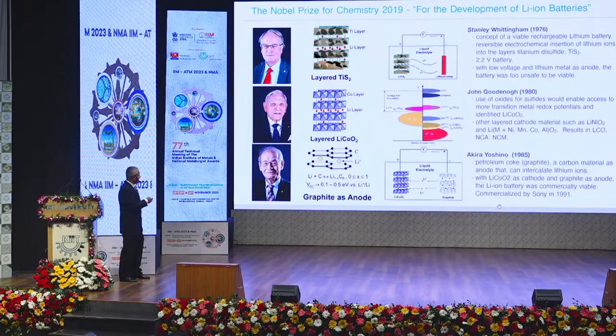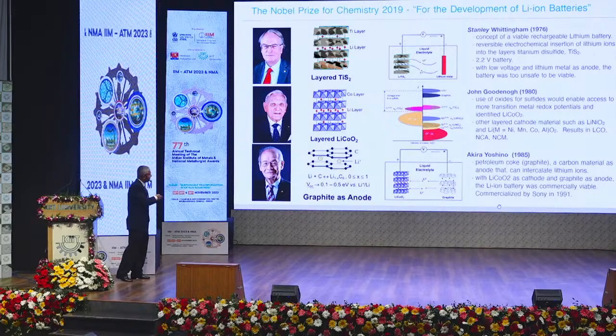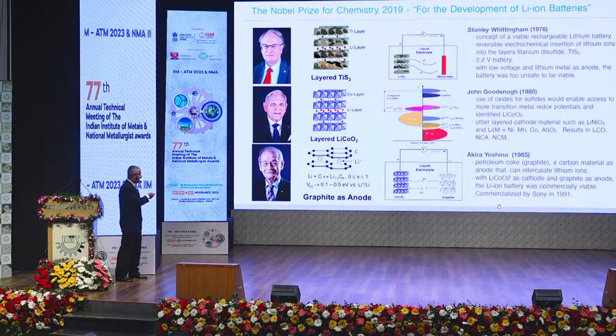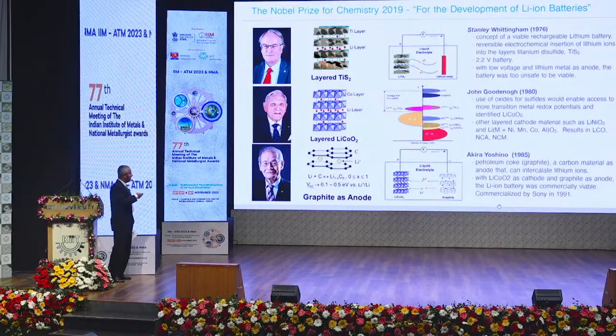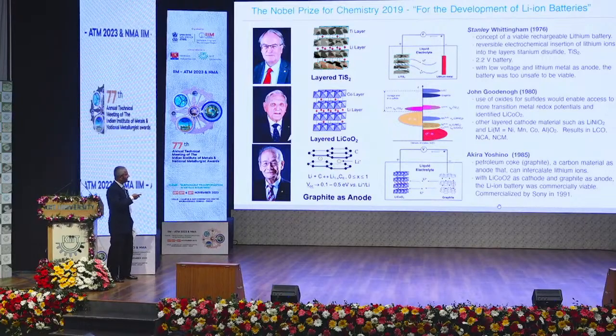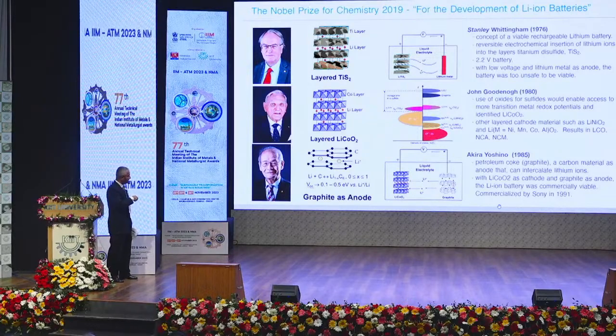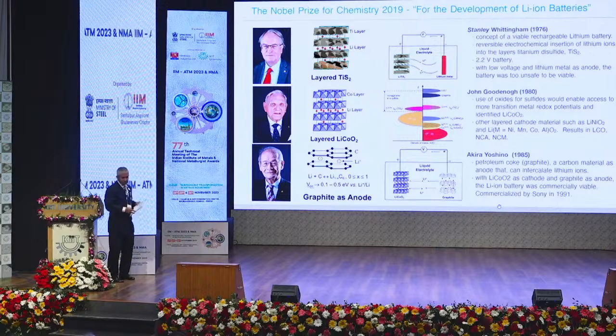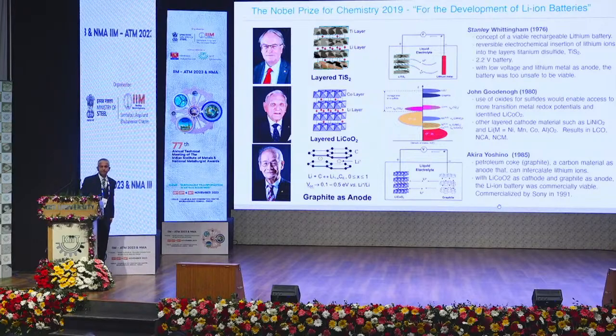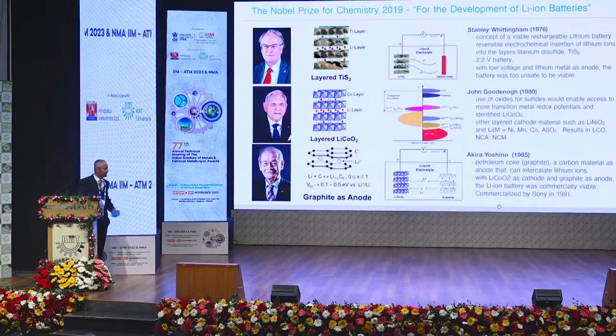After that, other layered cathode materials such as LiNiO2 and NMC were identified. In 1985, Dr. Yoshino found that graphite can be used as the anode, which can intercalate lithium ions. So with lithium cobalt oxide as the cathode and graphite as the anode, the battery was commercialized in 1991. So that is the chemistry we use in our phones today, mostly.